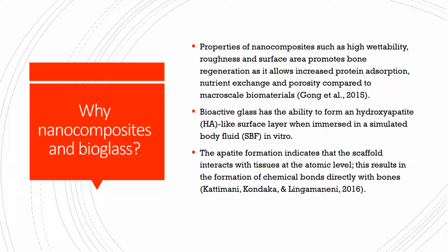Bioactive glass itself already has the ability to form a hydroxyapatite surface layer when it is immersed in simulated body fluid. The apatite formation proves that the scaffold interacts with tissues at the atomic level, which can result in the formation of chemical bonds directly with the bones.